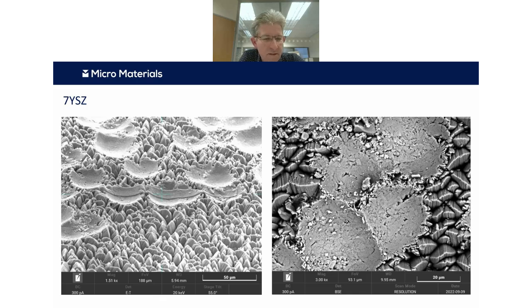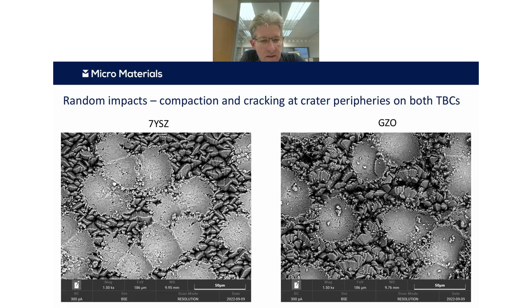So if we look at the sort of damage that we get in these random impact tests, now we can see a couple of different images there. You can see that we're getting the same sort of compaction that we see in the repetitive single impact tests, and also that cracking is occurring between these impacts when they start to be too close to each other, essentially. So if we compare the two coating systems by eye, they look reasonably similar.